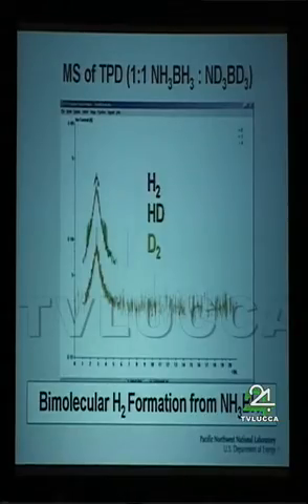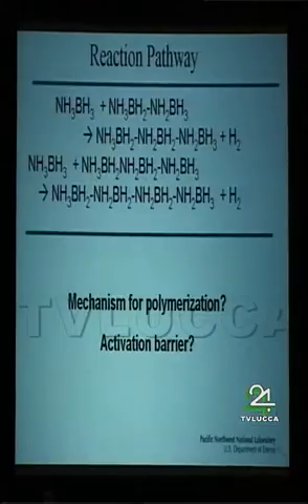So you form hydrogen from the hydridic and protic hydrogens that are in close proximity to each other. Whether the reaction is concerted or stepwise, that still needs to be determined, and we want to get more detail into kinetic isotope effects and also some Arrhenius treatment of the data. So you can start to draw some sort of back-of-the-envelope scheme of this thing where it undergoes some sort of dehydropolymerization reaction, and you just keep building this stuff up, and it releases hydrogen with each subsequent step. So what is the mechanism for this polymerization, and what's the activation barrier?